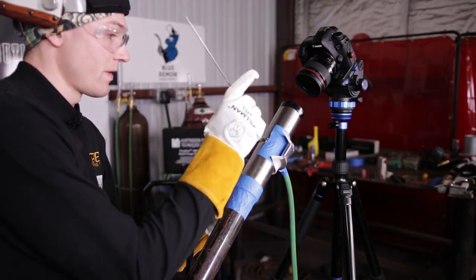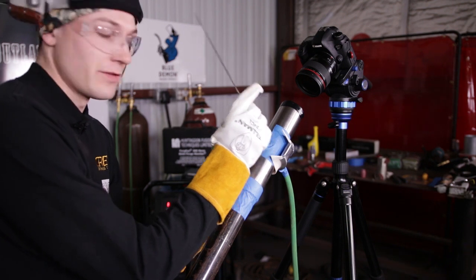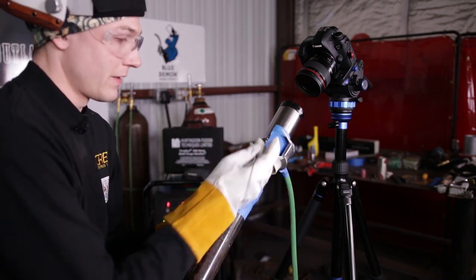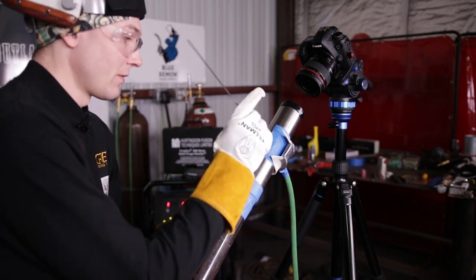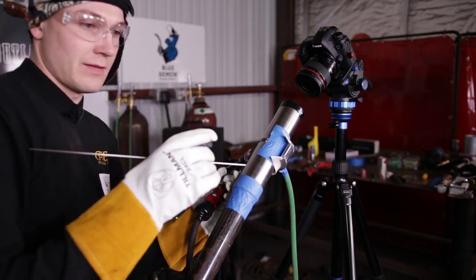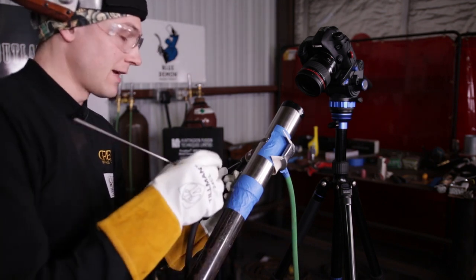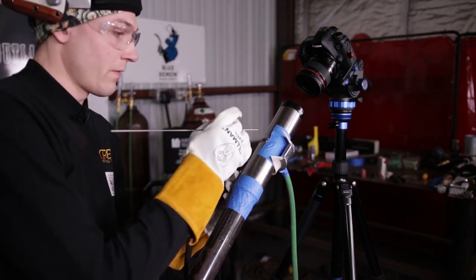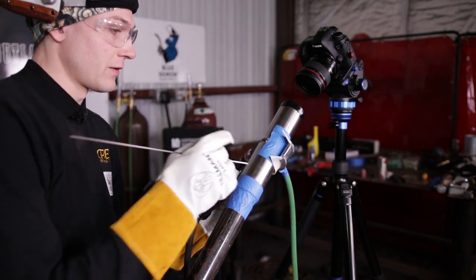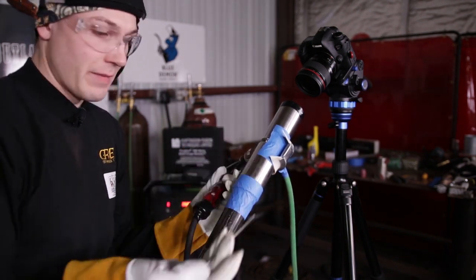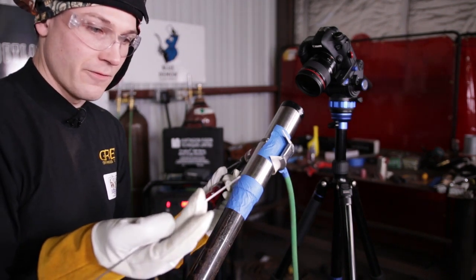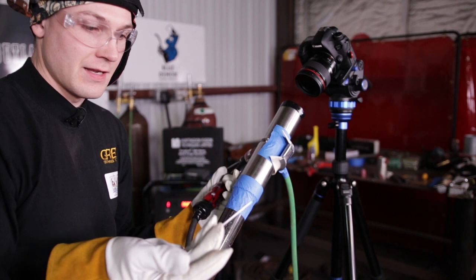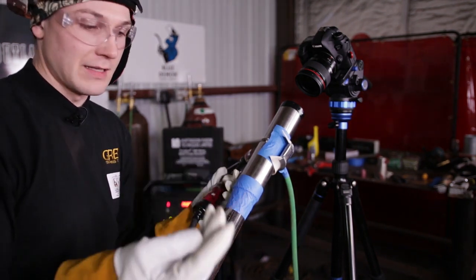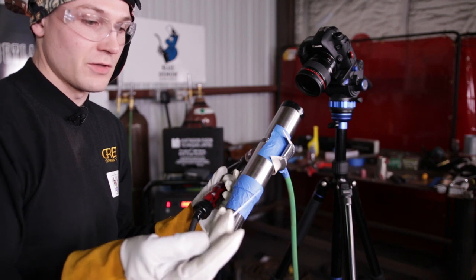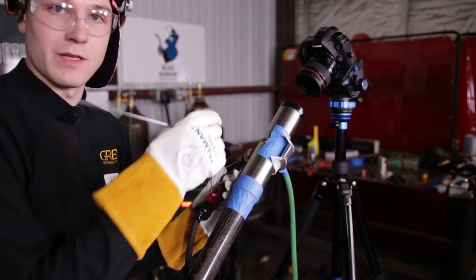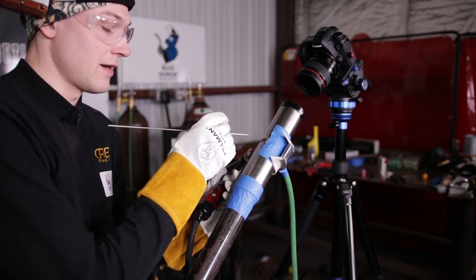Also, when you're welding, since titanium is in backfeed, it's a little bit easier to back purge it than it is to have the filler on the outside of the pipe, because it becomes very sticky. So when you backfeed, and it doesn't have to be just titanium, it could be stainless, nickel alloys, duplex, etc. If you have a very good quality of purge internally, like 25 parts per million or less, when you remove the filler metal, inspect the tip of the filler metal. If it's nice and silver and there's no heat tint, then it means that there's 25 parts per million or less. If there's a light straw color, browns, blues, or purples, it gives you an indication of what the atmosphere internally inside the pipe is going to be, with how many parts per million of oxygen is inside the pipe.